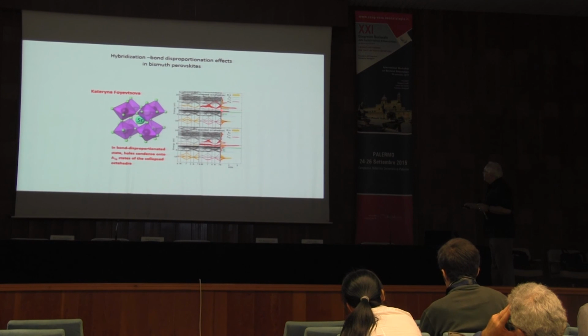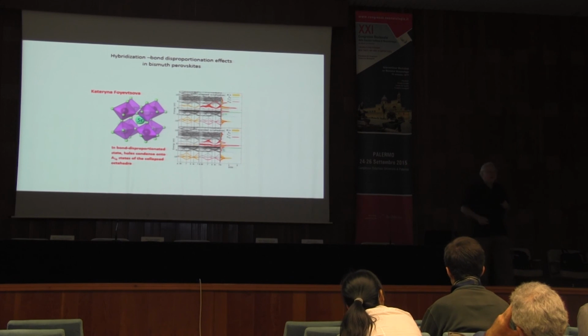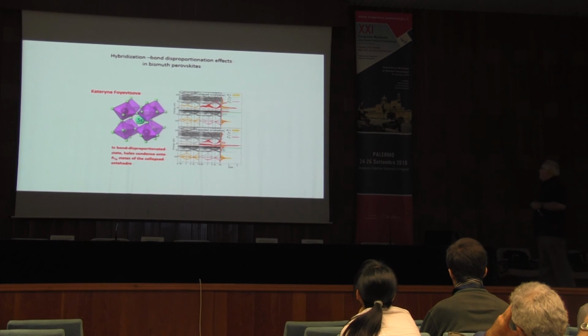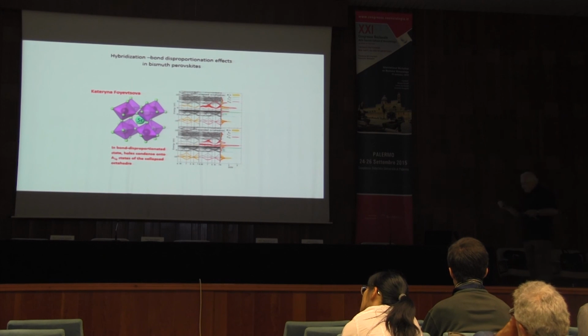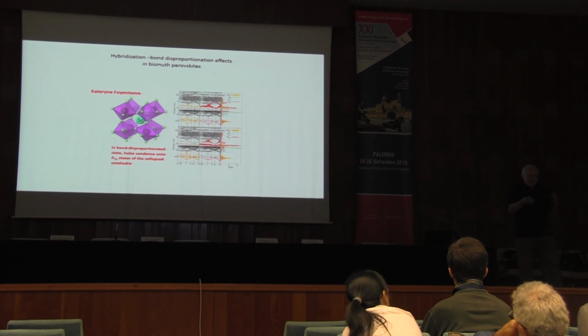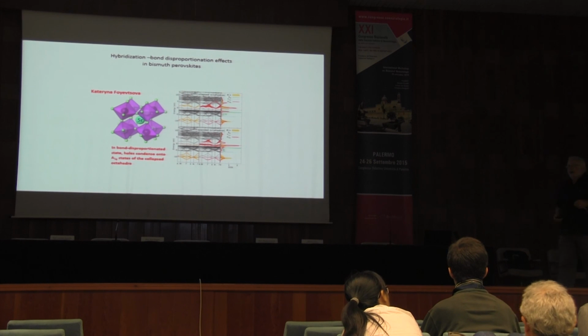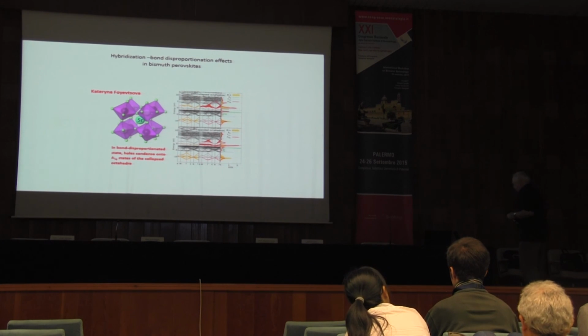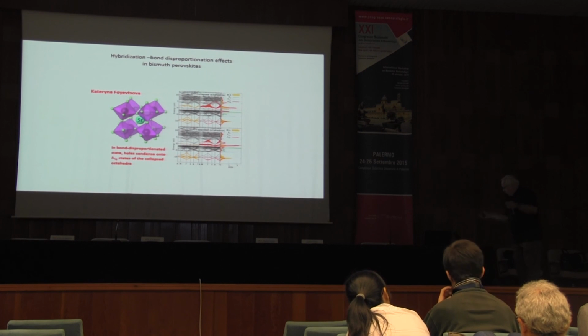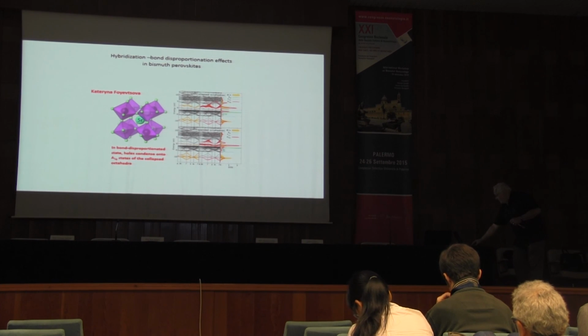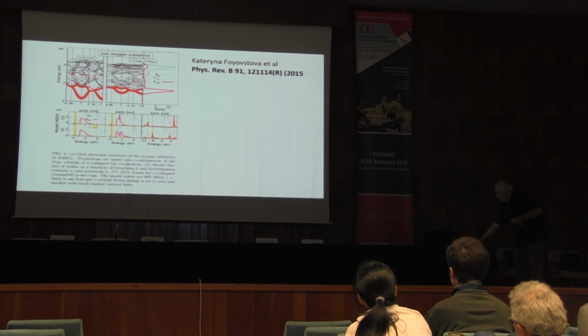Also a sharp band, just below the Fermi energy. That is the band which corresponds to the EG symmetry orbital of oxygen states. And somehow or other, with sufficient doping, that changes the whole story, but I think the bipolaron-like concept still probably holds, and that you really have a kind of bipolaron-like Bose-Einstein condensate or something for the superconductivity in this system.